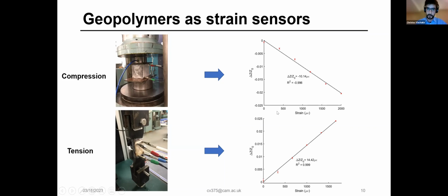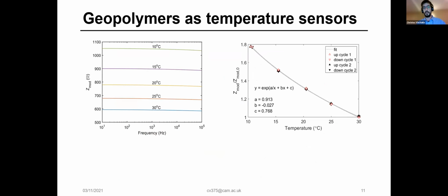And by assessing the sensing capacity under compression and tension, we're also able to extract the gauge factor in each situation, which is about 10 for compression and about 14 for tension. Moving on from strain, we can also use these materials as temperature sensors as well.